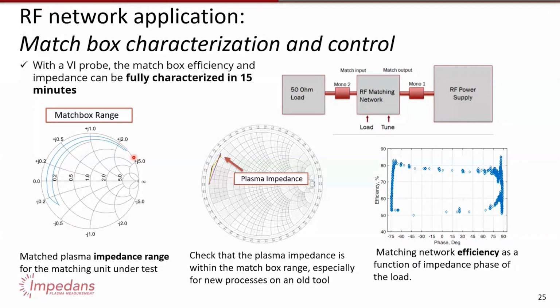Using a VI probe, you can actually map out what the impedance is of the plasma. We have a video on YouTube about this. You can contact us if you want us to send a video on how exactly to do it. But essentially, you actually run things backwards. You go power supply to the output of the match, and then the input of the match is connected to 50 ohms. So you're looking backwards through the matchbox, and you move both tuning caps from start to stop and start to stop. And this plots a map of your matchbox, and your plasma impedance should be within this map.